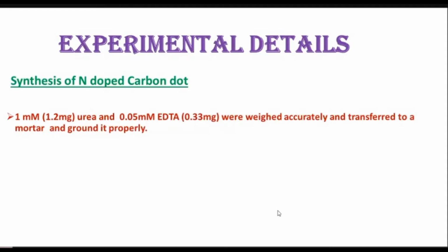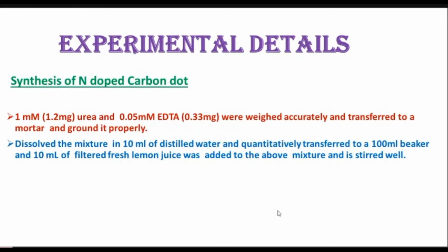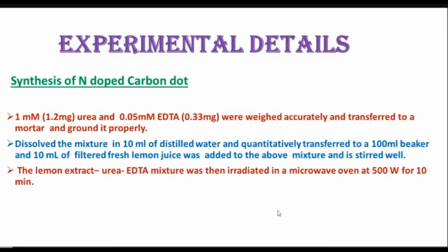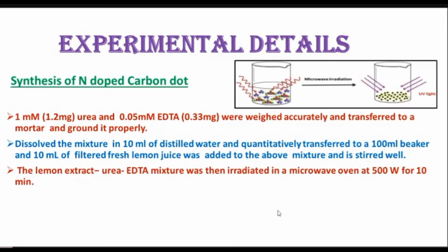We take urea and EDTA in a mortar and grind them properly. 10 ml of distilled water is added into it and it is transferred to a beaker. 10 ml of filtered fresh lemon juice is added into the mixture and it is irradiated in a microwave oven at 500 watts for 10 minutes.